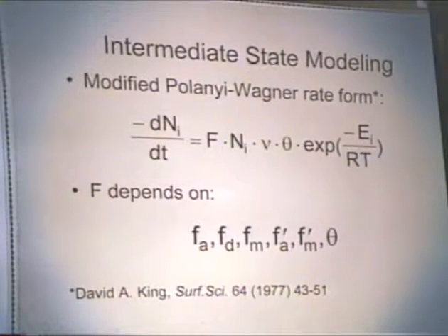So F itself has dependencies on a number of factors, which include the probability that once a desorbing species has gotten into a precursor state, it will readsorb, that it will desorb, or that it will migrate to another precursor state, as well as the probability that once it gets into a precursor state over an occupied site, it will either desorb or migrate, because it can't readsorb over an occupied site. And F also has some θ dependency built into it.